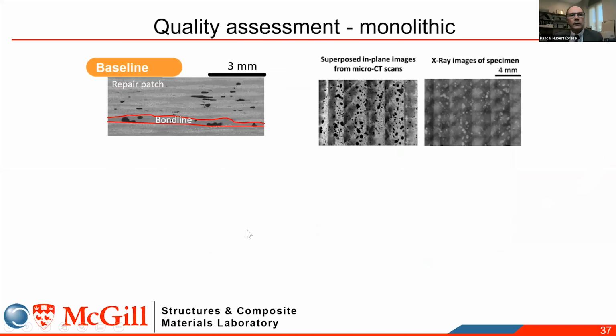So first, let's look at the quality of a standard adhesive. You can see here the bond line. And you can see the porosity of the bond line, and the repair patch even has some porosity. If you look at the image of that bond line from the top of the laminate, you can see the different steps in the joint. And you can see from the micro CT and the X-ray, you can see all the porosity.